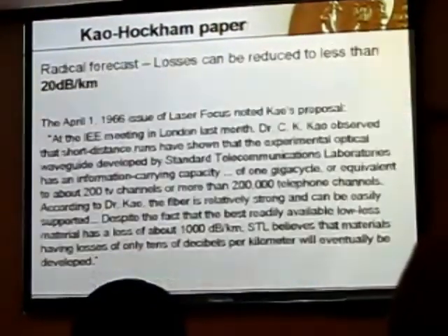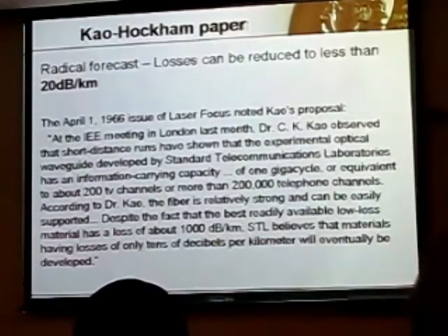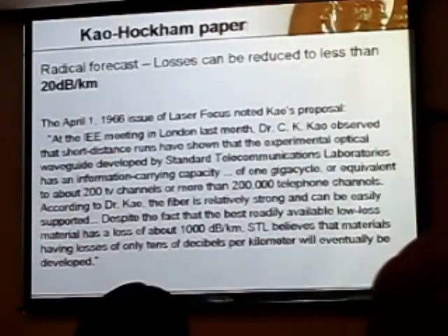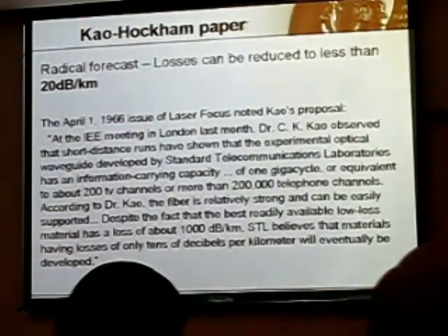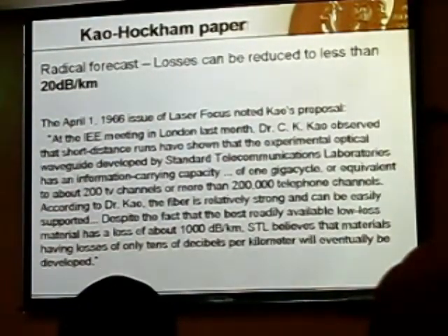So this paper is, it's very radical. Remember, we are at 1000 dB per kilometer, and now he comes to this meeting and says, look, the problem is not silica, you can get silica down to 20 dB per kilometer.